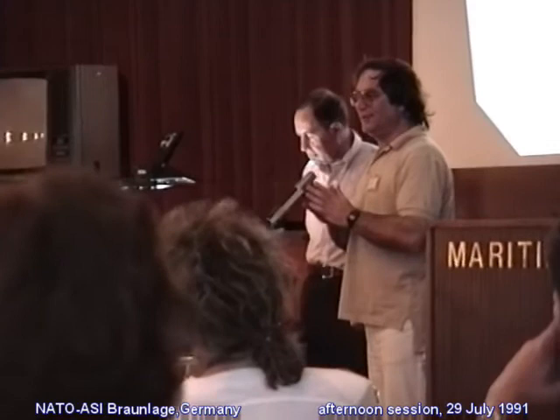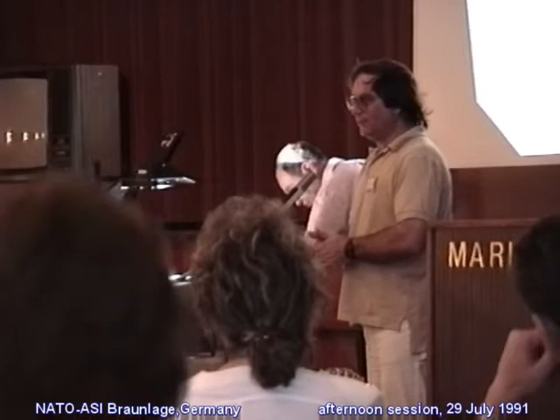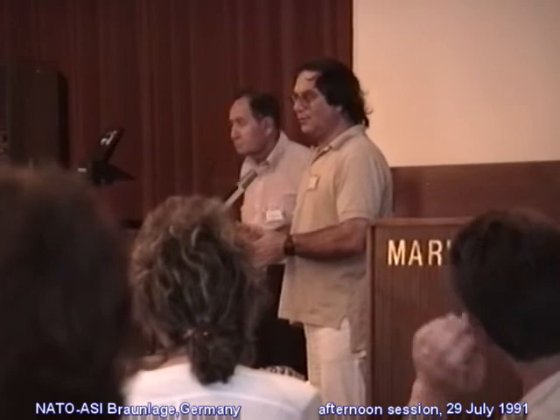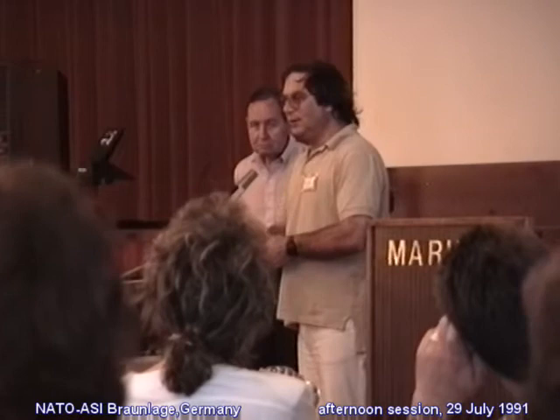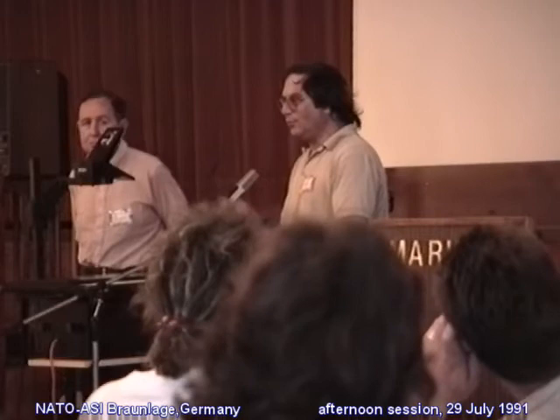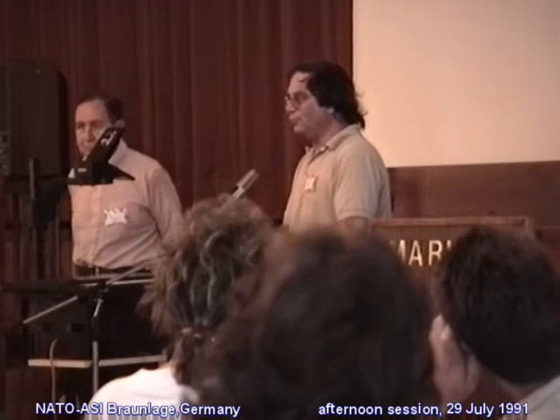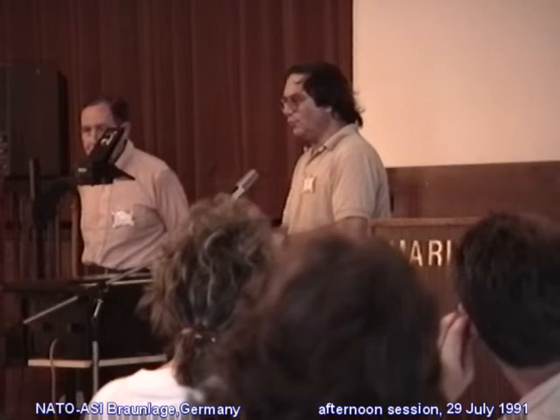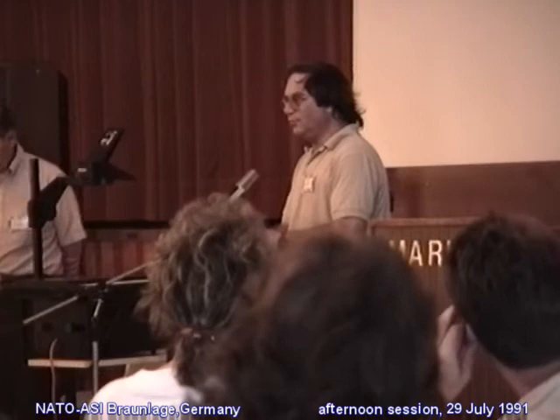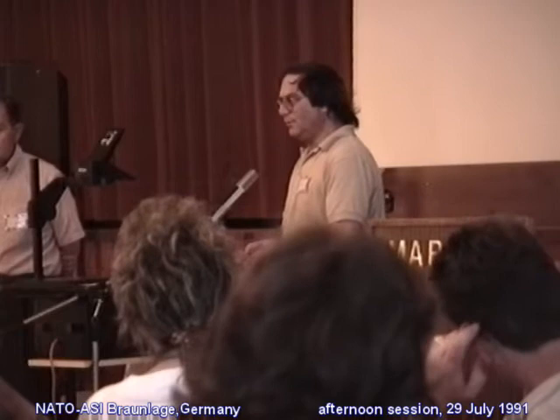Professor Tabor a question, and that was a very fundamental thing that you mentioned about separating surfaces, and if one, and there's an elastic energy stored as they stretch, and then that's presumably recovered as they separate if one does it slowly enough. Now, in many practical situations, one obtains instabilities regardless of how slowly one does it. So that one cannot, in practice, actually separate surfaces slowly, because they're going to jump apart at some point. And the same happens at the atomic scale when you have fracture or crack, it doesn't matter how slowly you do it, the bonds just pop, and they go pop, pop, pop, as they go. And therefore, thermodynamically, one loses, and it must be an irreversible and therefore dissipative process.